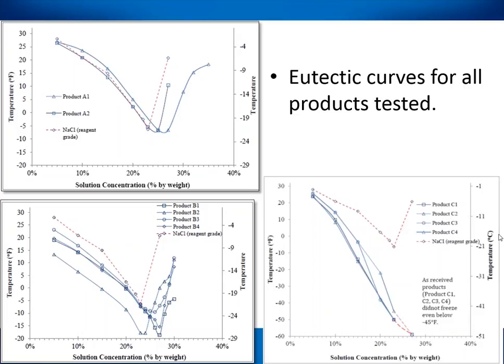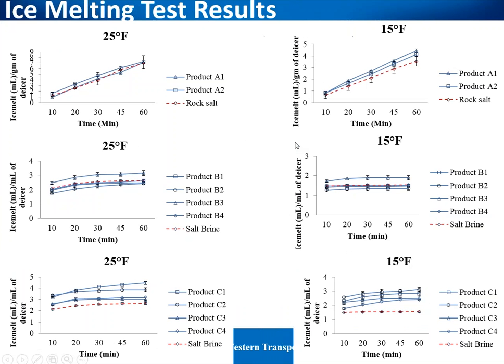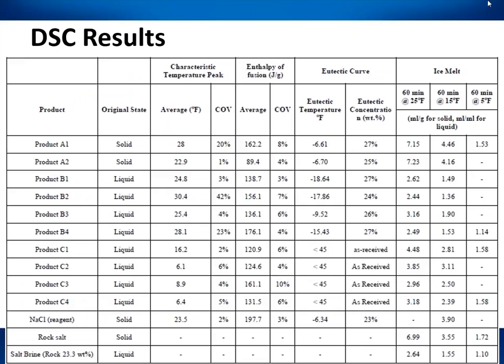Hey, Laura, this is Ron Wright. In this, did you guys, I can't recall, did you guys have an effective temperature range that you helped establish using the DSC? So here's the chart with the DSC data. And you can see here the characteristic temperature peak for the different products, as compared to the eutectic data and then the ice melting data. So in terms of bracketing an effective temperature range, we did not do that for this project. But we did characterize the characteristic temperature using the DSC, the eutectic temperature, and then the ice melting capacity at various temperatures for each product.